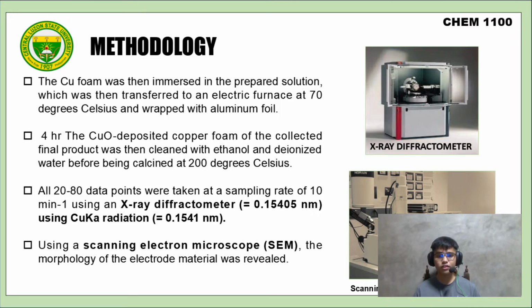which was then transferred to an electric furnace at 70 degrees Celsius and wrapped with aluminum foil. For several hours, the copper oxide deposited copper foam of the collected final product was then cleaned with ethanol and deionized water before being calcined at 200 degrees Celsius. All 2θ data points from 20 to 80 degrees were taken at a sampling rate of 10 minutes.